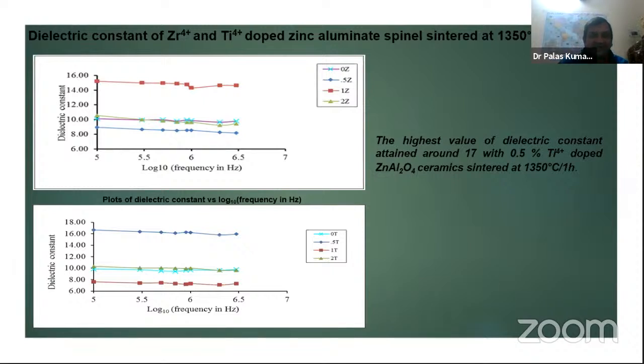And for titania, 0.5% gives the best result, and for zirconia, 1% gives the best result. Just recall, in the previous slide we saw the microstructure for 0.5T, that is 0.5% titania, and 1% zirconia. The structure fits very well with this observation, the trend of the dielectric constant.